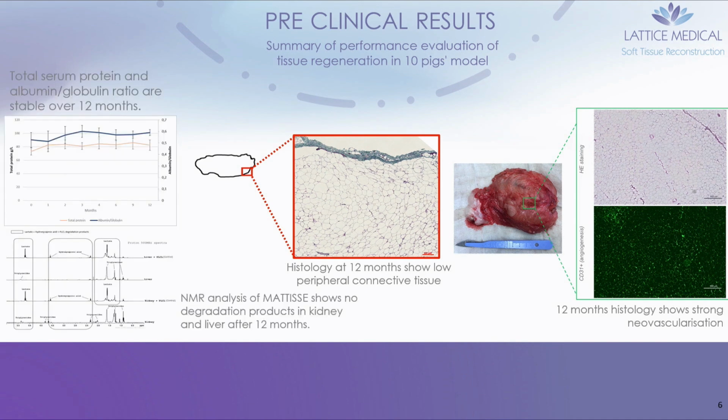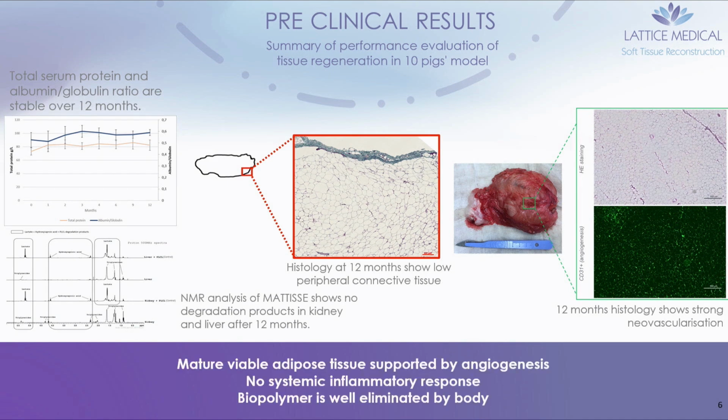Finally, we checked the absence of systemic inflammation, and there's no change in serum protein levels over time. NMR analysis also did not show any accumulation of degradation products of the implant in kidneys and liver after 12 months of implantation.